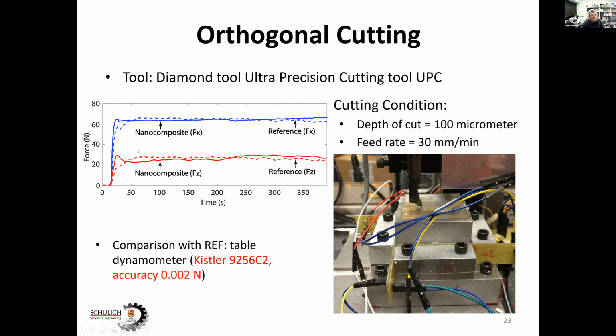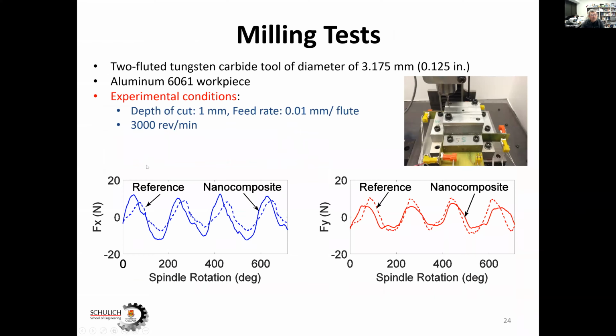And this is sort of the static measurement, whereas for the dynamic measurement, this is for milling operations at 3000 RPM. Both the reference and our sensor exhibited fairly decent peak-to-peak forces. So we are happy and published a bunch of papers.